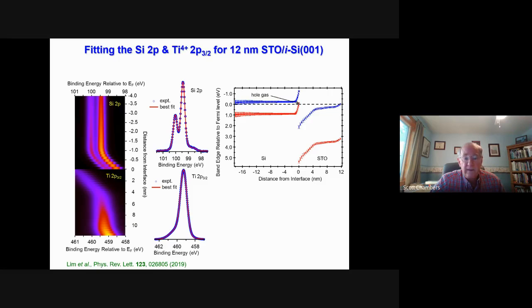First of all, the valence band maximum in the silicon climbs above the Fermi level right at the interface, which explains the formation of the hole gas. Also, the conduction band minimum of the STO climbs above the Fermi level right at the surface, which explains the surface depletion. The valence band offset is easily gotten.